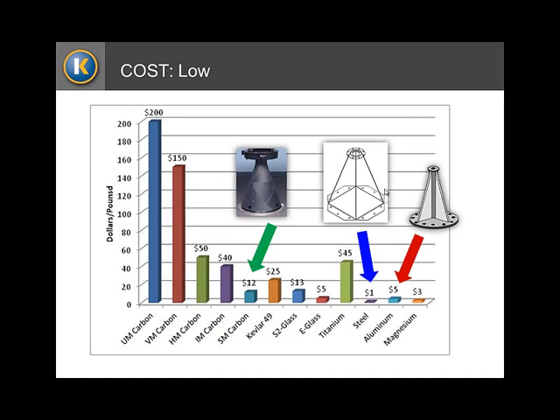Can't forget, though, about cost. Aluminum, just raw aluminum, say is on the order of $5 per pound. That's pretty cheap compared to the carbon materials. All the carbons are pretty far up there. I mean, way up there for ultra-high modulus carbon on the left. But if you look at standard modulus carbon, it's one of the lowest economic grades of carbon at $12 a pound. That's still more than $5 a pound for aluminum. In fact, if this could be made out of sheet metal, which I'll talk about in a little while, it could be just $1 a pound.